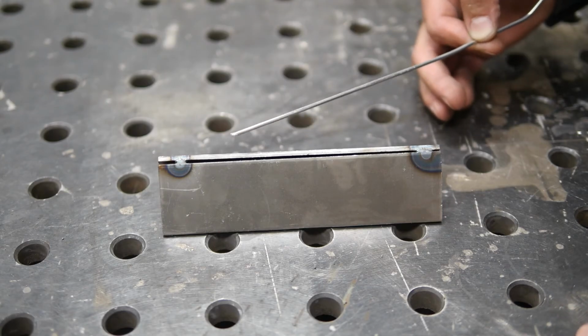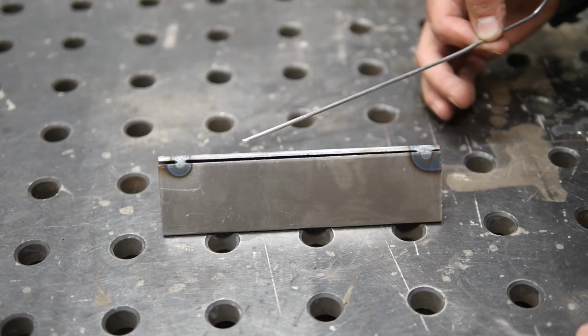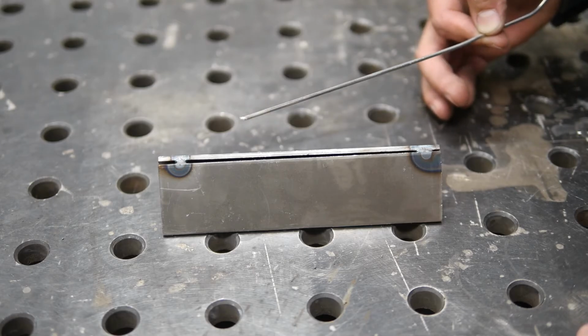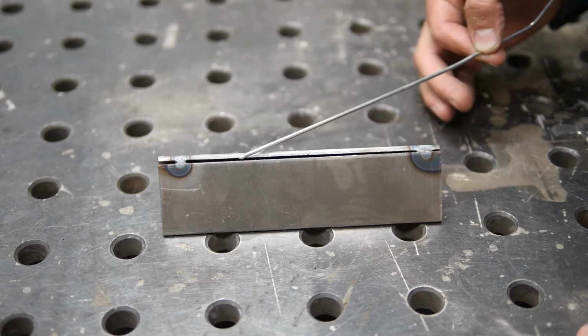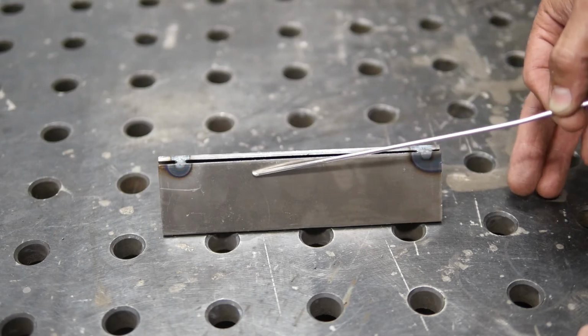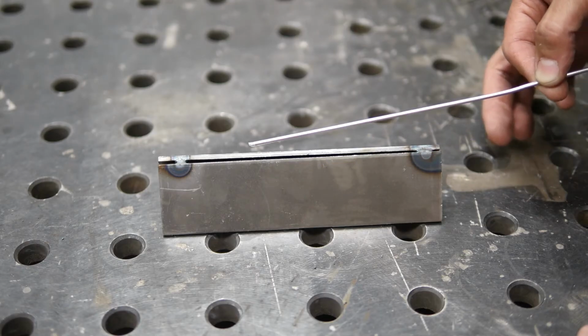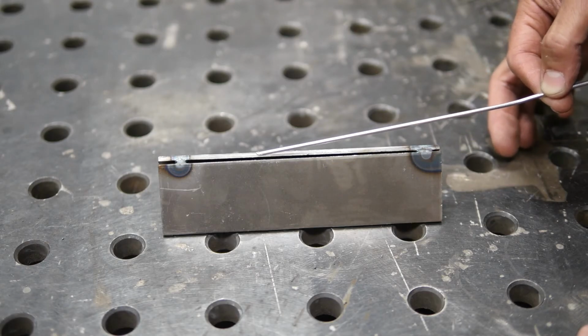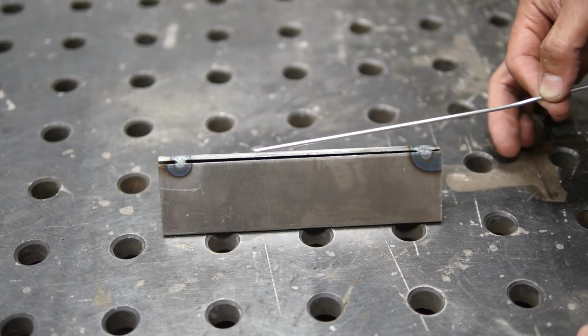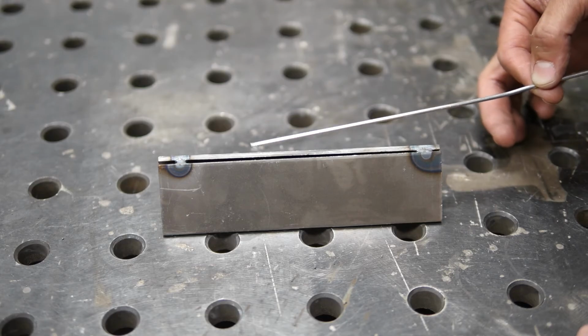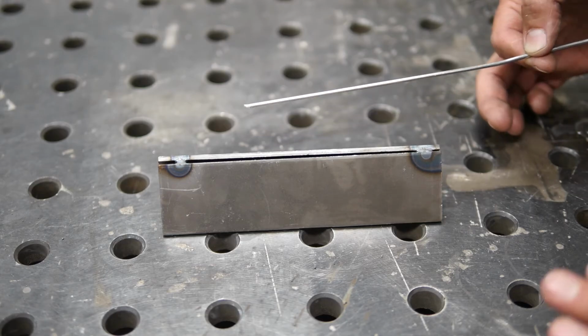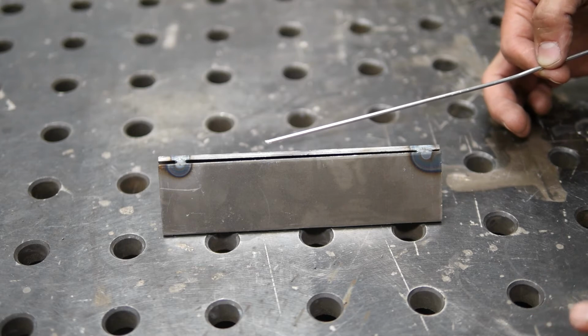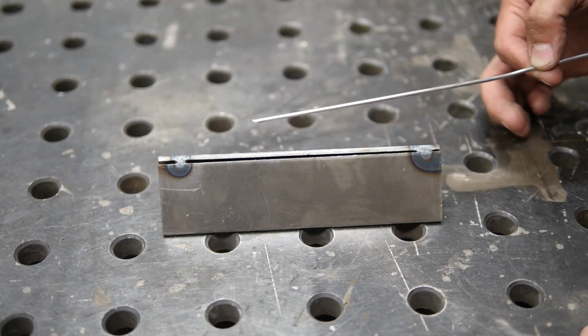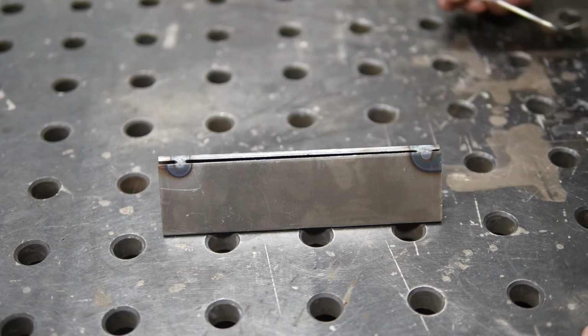So since they're not touching and there's a gap, we actually have to turn the wire feed speed down. And the reason for that is because edges are more vulnerable to heat than the bellies of the plates or the middles of the plates. And since the two parent metals aren't touching, they're both going to have to bear the brunt of the heat load individually, and this could cause us to blow through. I'm going to leave the settings at 240 on the wire feed speed. I'm going to try to weld this, and we'll see what happens.